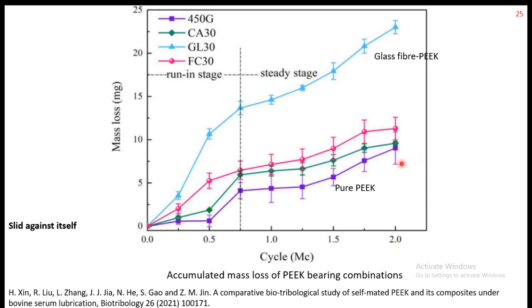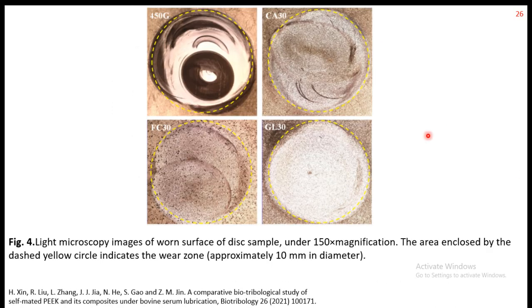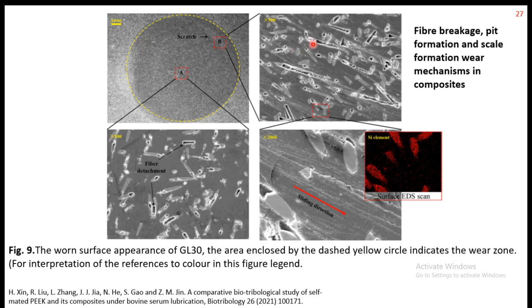It was not compared with the metal, so we can only see the results of this polymeric material against polymeric material. This shows the wear surface, which gets completely polished, and here you can see this is the glass fiber reinforced PEEK where we get a higher wear rate. So everything is within our expectation, and hopefully the polymeric material against polymeric material might be another choice.